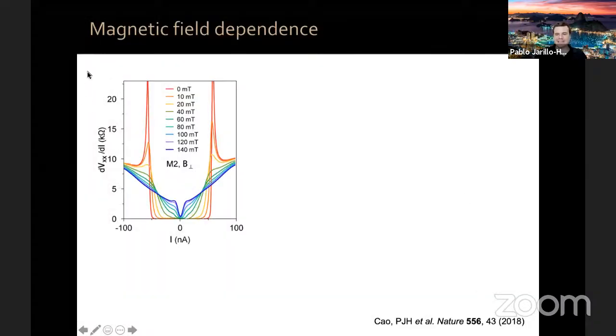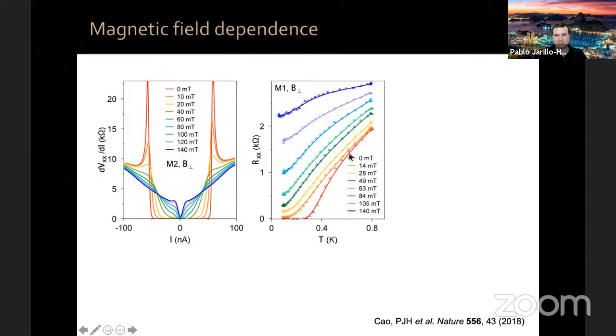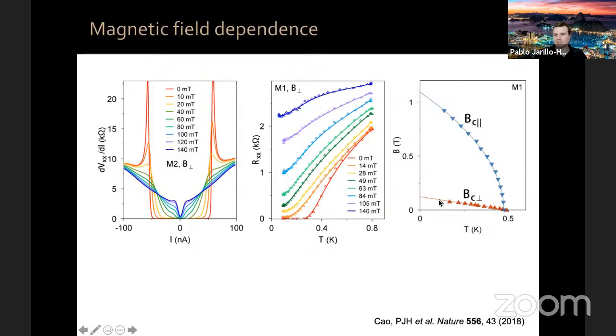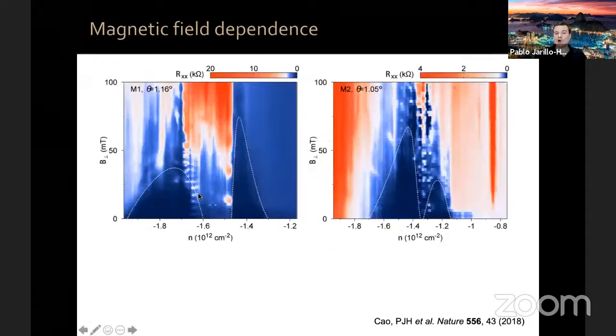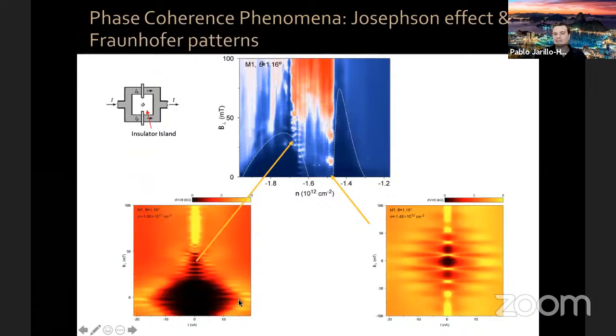Okay, so of course, magic angle graphene has a response in a magnetic field. You can see the response here. You can also look at the resistance versus temperature at different magnetic fields and extract the superconducting coherence length. You can do this at perpendicular and parallel magnetic fields. It turns out the parallel critical field is very, very high because it's a two-dimensional superconductor, so you don't have orbital effects, or they're very weak in the parallel direction. And in fact, you can do all of this continuously as a function of density, so you have domes in magnetic field. Now, you could see here that there seems to be noise. It's actually not noise. These are Fraunhofer-like oscillations of the critical current. This is Josephson phenomena: when you measure the critical current as a function of perpendicular magnetic field, you can see these Fraunhofer-like oscillations close to the superconductor-to-insulator transition, where your system breaks into islands. Now that's a longer answer than you asked for, but yes, it's a type two superconductor.